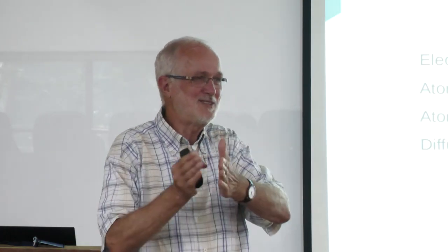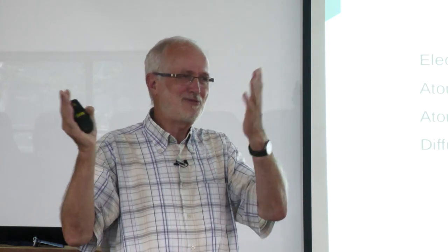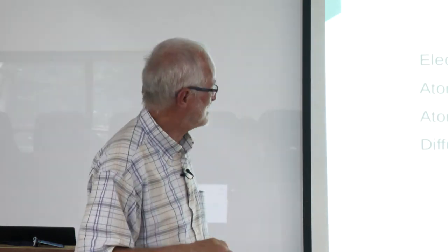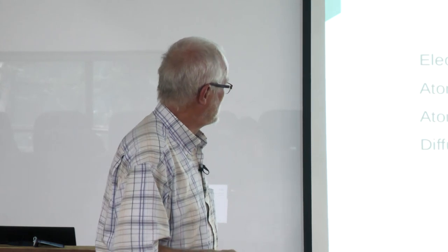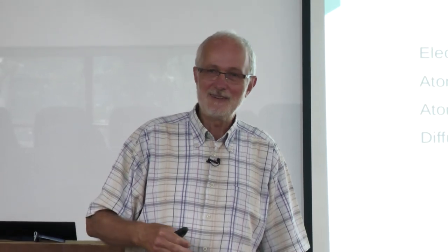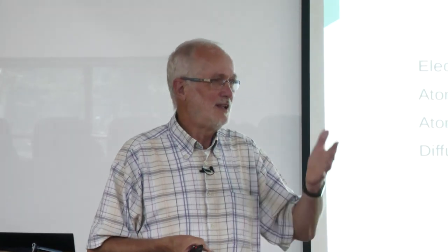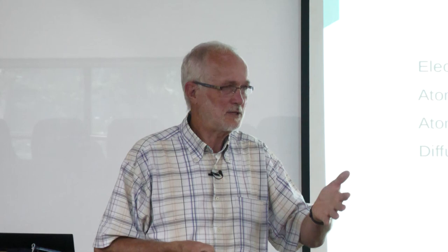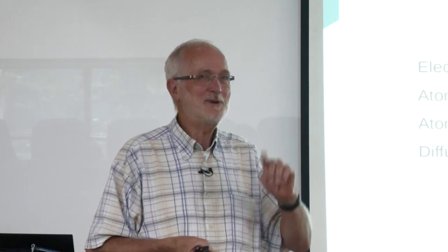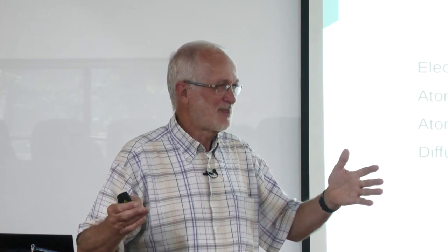So you get diffusion distances. I think on one of the next slides, perhaps I calculated, you get diffusion distances perhaps of micrometers or so, yeah? Not of centimeters, perhaps millimeters, depends on temperature. Yeah, this is what is written here. For diffusion, you need very long times. Yeah, I mean, of course, for technical diffusion, if you want to do a precipitation reaction, you want to harden aluminum, it must be done in, say, half an hour or so, or 2 hours. Yeah, nobody hardens an alloy, not nobody, but few people, over a time of a year or so. Yeah, but still this happens.